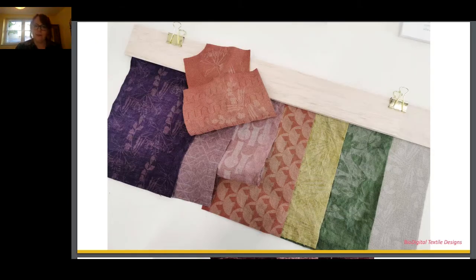These natural linen textile samples have been designed by combining the bio-dyeing processes with the digital laser treatment. The linen was pre-treated firstly with oak gall to add tannin, secondly mordanted with Symplocos, which we found to be the most effective biomordant treatment. Then the printed design features were applied using the laser, and finally the textiles were dyed using a range of plant-based natural dyes. This particular colour palette was achieved using mixtures of madder, weld, chlorophyllin, woad, and satinwood dye extracts.